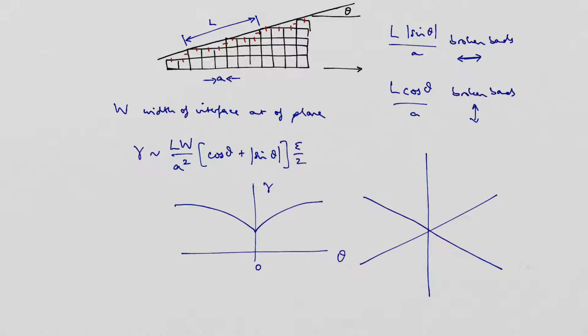Okay. So this is called a gamma plot, and it's a polar plot, and I'm plotting theta as the angle around. And the distance from the origin is proportional to gamma. So let's suppose that here is gamma 001. So theta at this straight up position corresponds to a 001 surface.